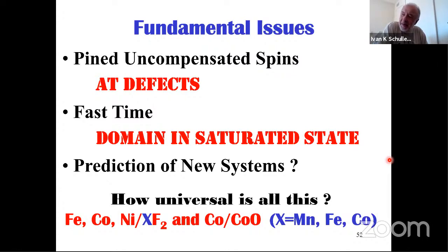But maybe one should consider that because of the following. The ordering of the ferromagnet, there is no such a thing as zero field, of course. There is always some field. And depending on what is the magnetic structure of the ferromagnet, that may affect the magnetic structure of the antiferromagnet. Therefore, when you're cooling it down, the antiferromagnet doesn't cool as if it would be in zero field. It cools as if it would be in a finite field. So maybe there is some effect of the Earth's magnetic field, although that's very small, so I'm not exactly sure. But let me put it this way. Certainly the domain structure of the ferromagnet, we had a very recent paper like half a year ago with Rafael Morales, in which we showed that the domain structure in the ferromagnet affects the antiferromagnet, affects the exchange bias. Okay. I'm not sure I answered your question.